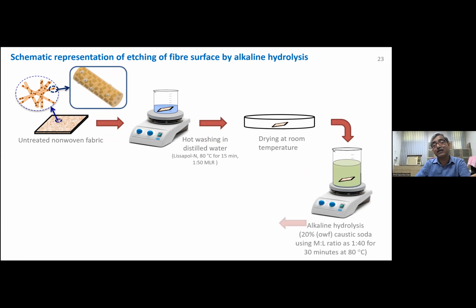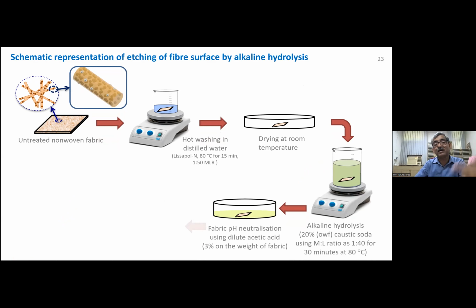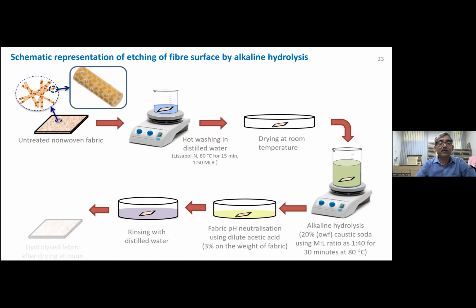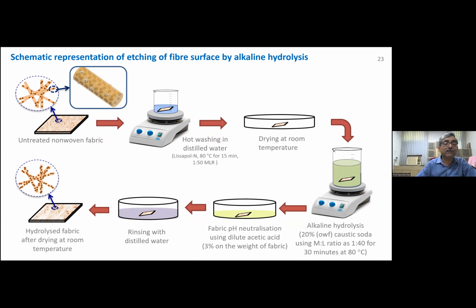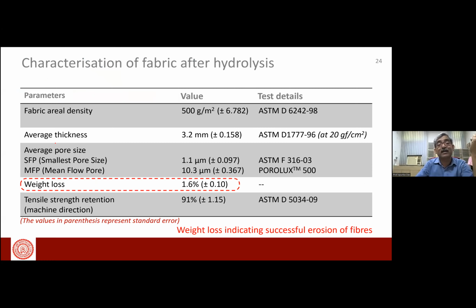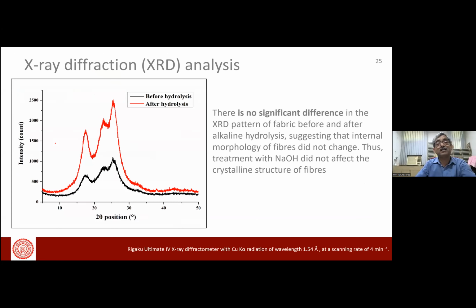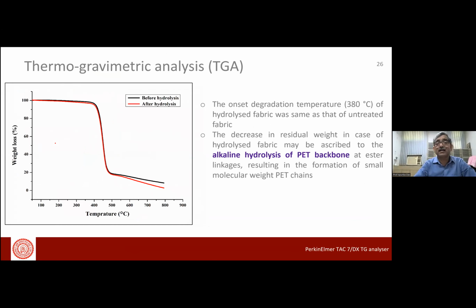So once we hydrolyze this non-woven, you will see the nanoparticles are exposed here. If you compare, a large number of nanoparticles are exposed on the surface, and this is actually improving the antibacterial effect. You can see these are the different studies which show the etching out of the nanoparticles at the surface.